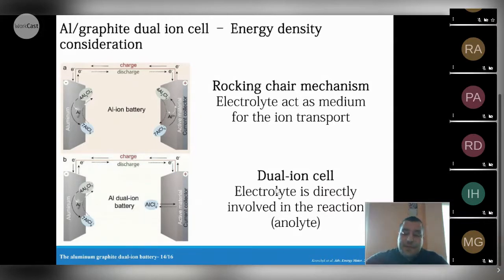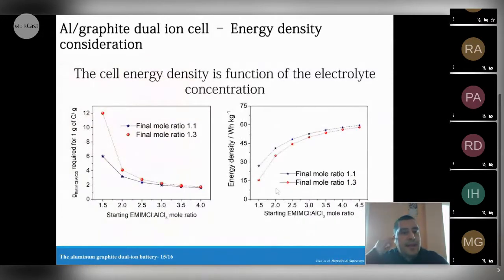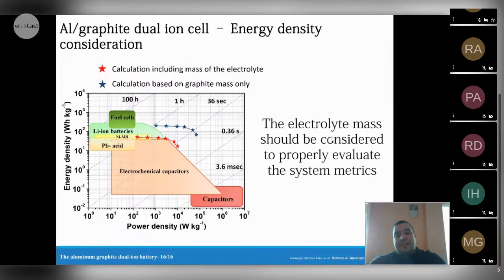For this reason, the electrolyte must be taken into account for the calculation of the energy density. And in particular for this kind of system, if we take into account the mass, the energy density of the system is a function of the concentration of the electrolyte. This is fundamental to properly determine the metrics of the system. In fact, if we calculate the energy density of the system based on the graphite cathode only, we are out of scale, let's say. While to determine the proper energy density, we need to take into account the electrolyte mass.